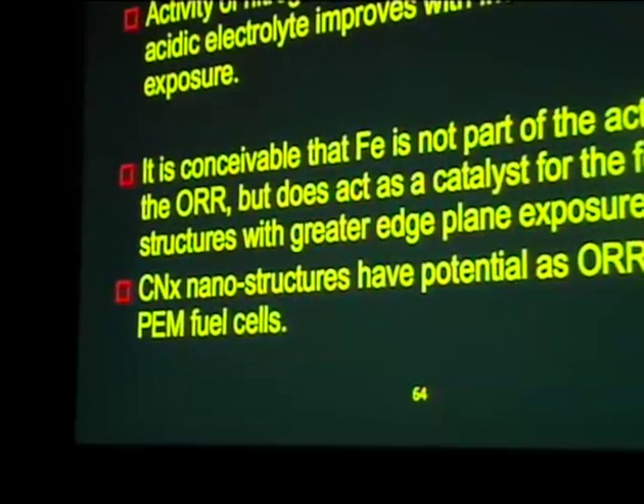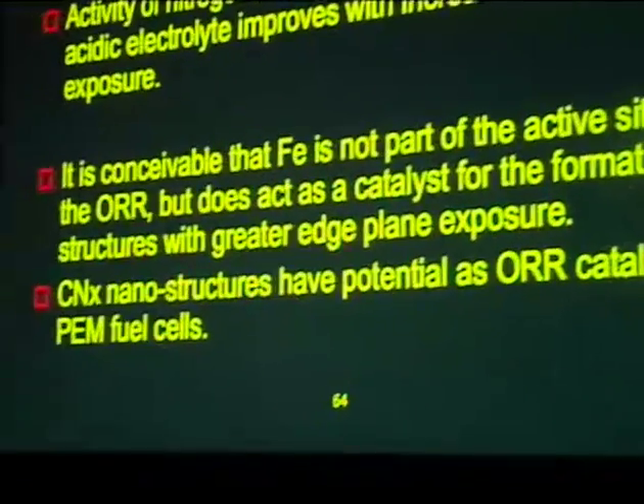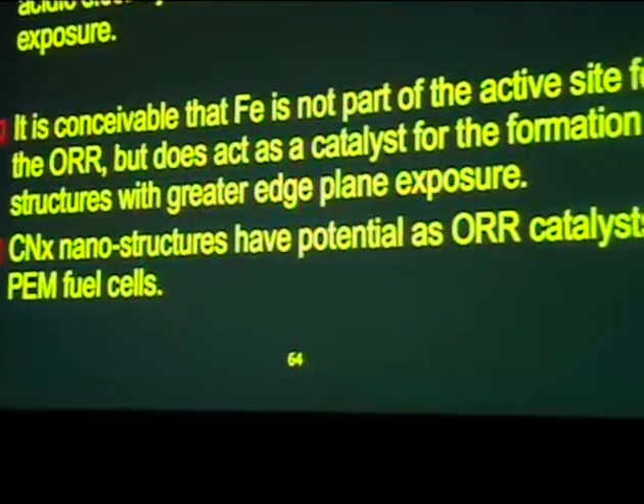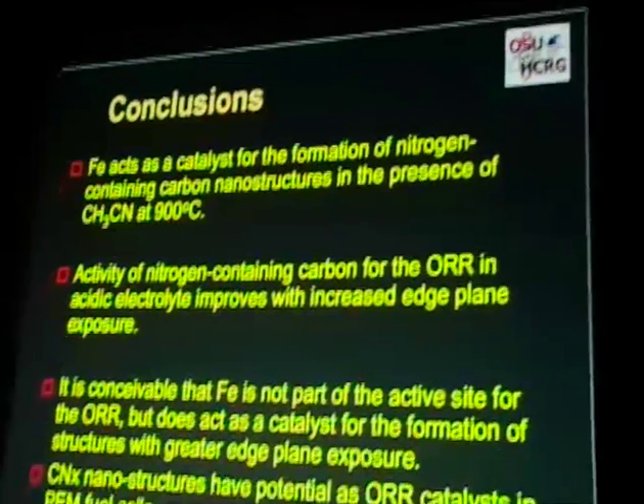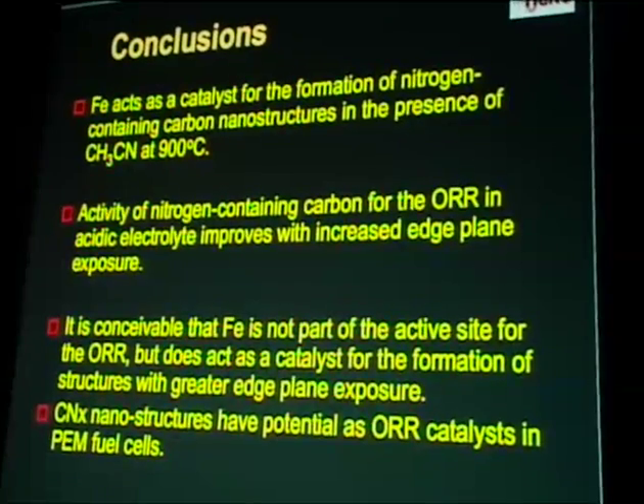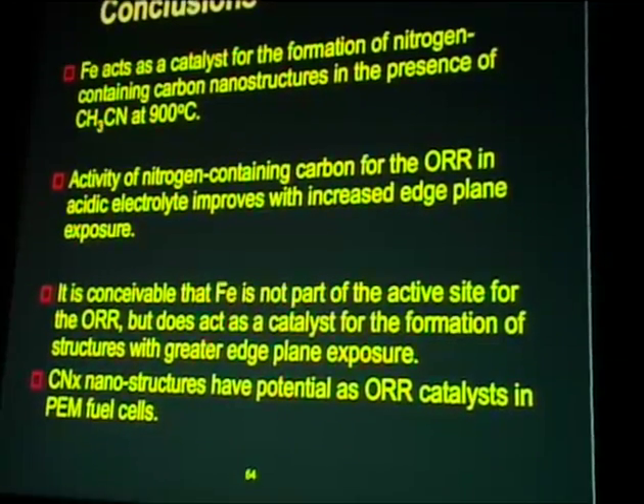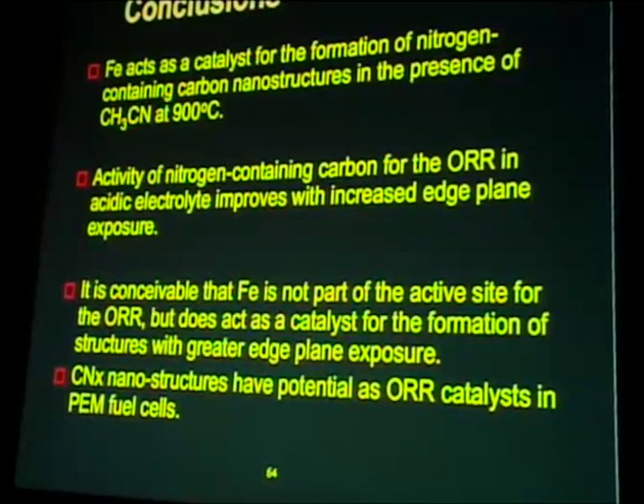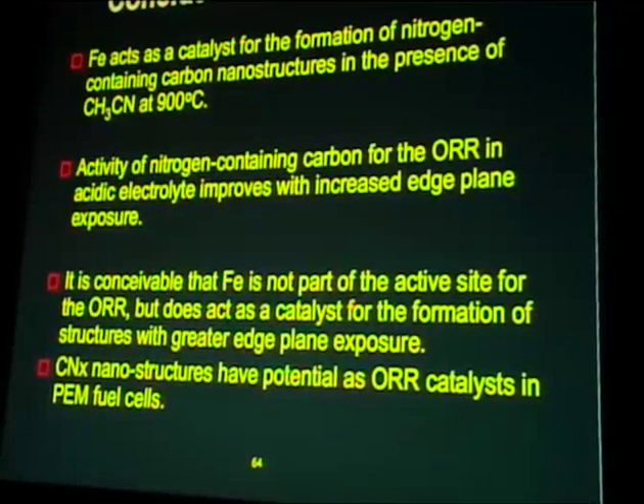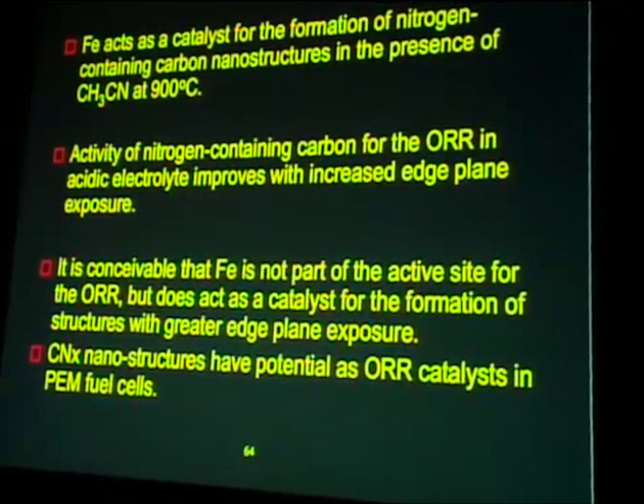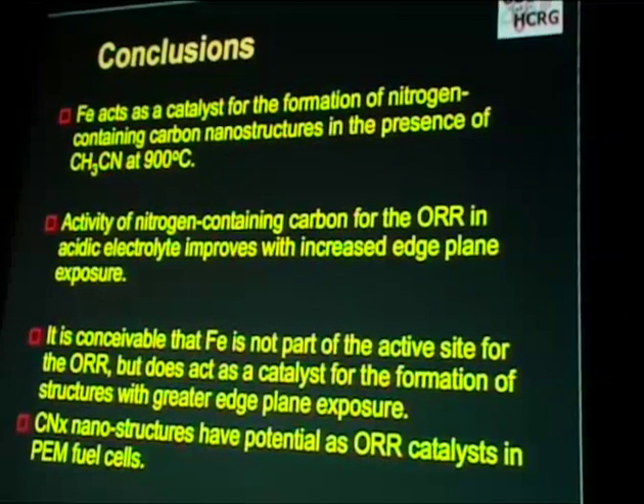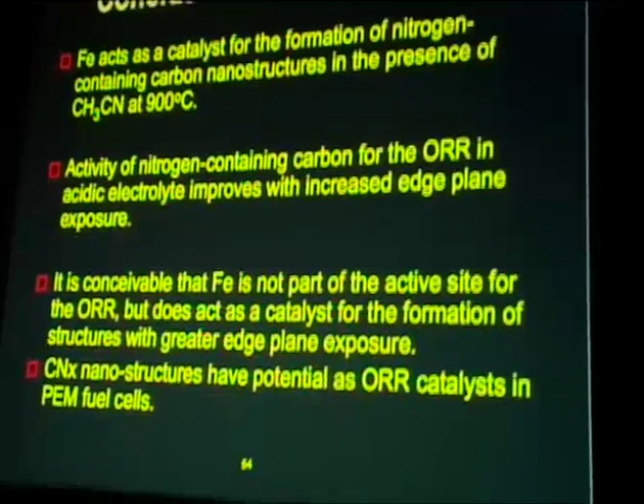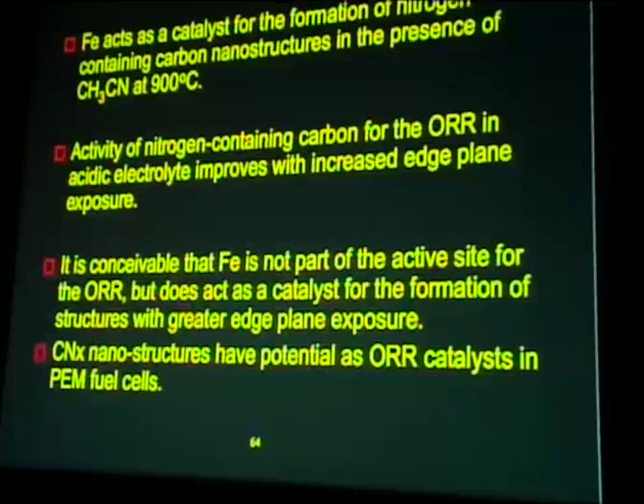So what we have seen is that iron is really acting as a catalyst for the formation of these nitrogen-containing carbon nanostructures, and the activity of these materials in oxygen reduction reaction improves with the increased edge plane exposure. And again, it could be related to pyridinic nitrogen, or pyridinic nitrogen can be a marker for the edge plane exposure. At this point, we don't have a definitive answer, and that's what we're trying to answer. And these CNX materials, these nitrogen-containing carbon nanostructures, have potential as oxygen reduction reaction catalysts in PEM fuel cells.